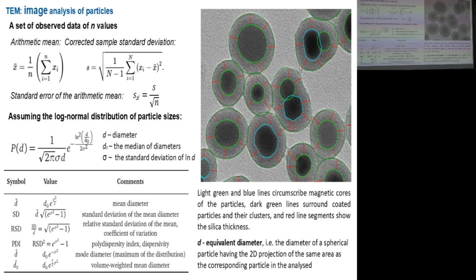And this parameter d0 is not the mean value, but it is the median value. If you want to calculate the mean diameter, you can use this expression. Also, if you are interested in the standard deviation of the mean diameter, it means standard error of the diameter, then you have to recalculate the median by using this formula, etc. So again, when reporting some values evaluated based on assumptions about size distribution, I recommend to declare the formulas at least in a supplementary. Then it's clear. Because there is a huge confusion in literature about these standard deviations.